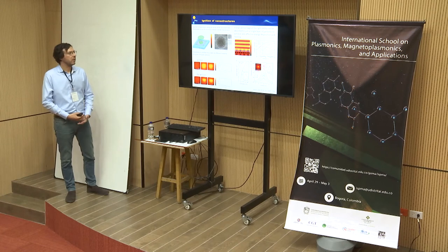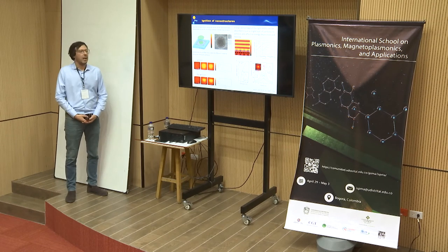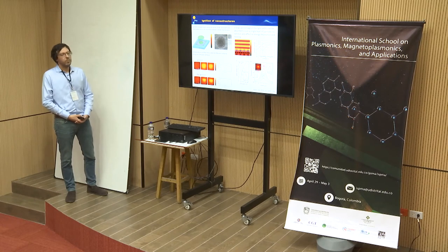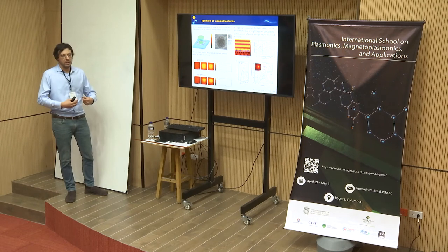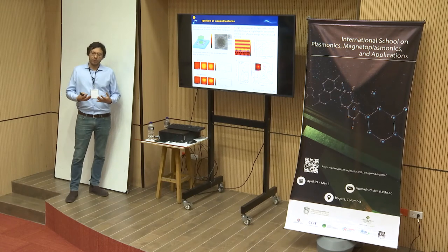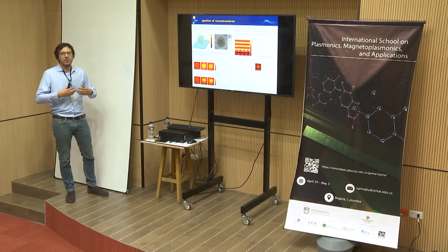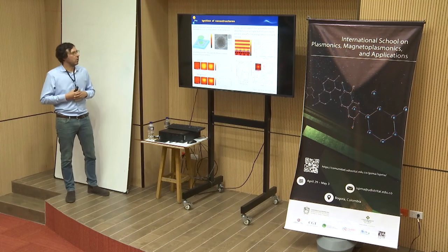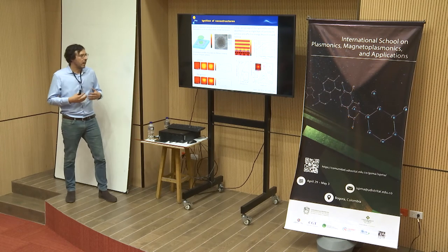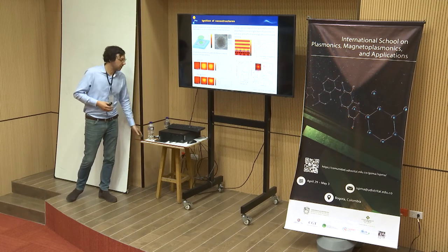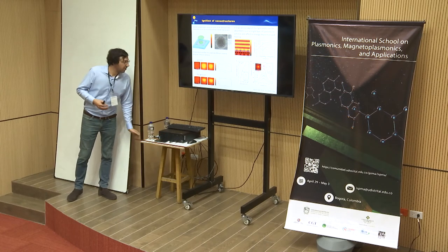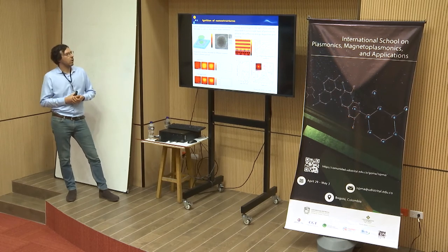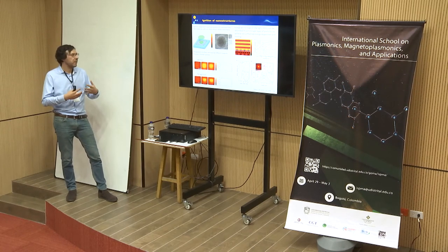And so aluminium nanoparticles, aluminium nanomaterials in general, are very interesting, and they are used, for example, as a propellant or explosive. This is because when you induce a very rapid oxidation, you can induce the ignition of this structure. Otherwise, if the rate of heating is very small, you will have just the oxidation. So oxygen will just go through the nanostructure, and we will form aluminium oxide. In this case, they create a highly intense gradient of temperature by using just one layer of aluminum resonator, creating several hundreds of Kelvin per second of gradient of temperature, and so creating the explosion of this nanostructure.